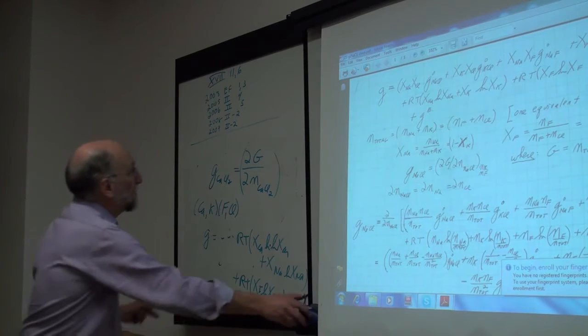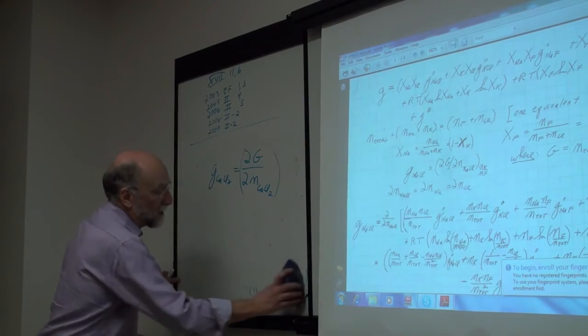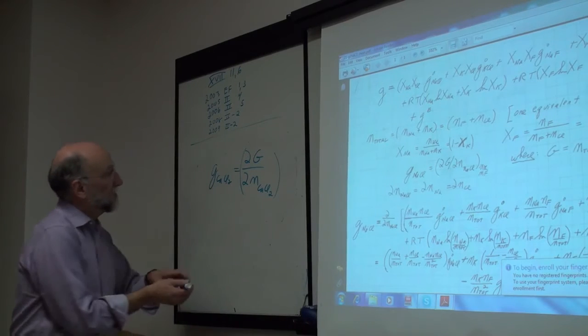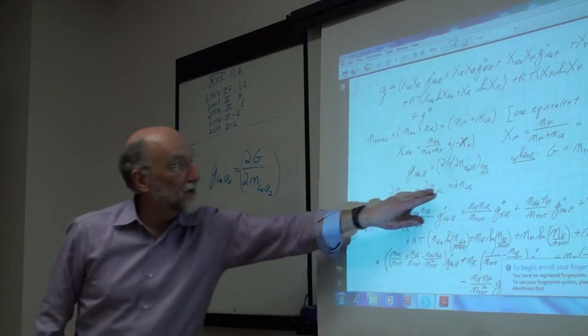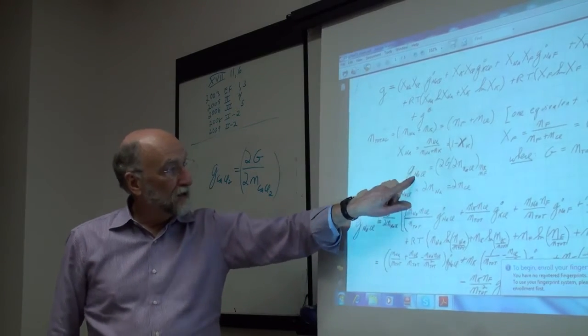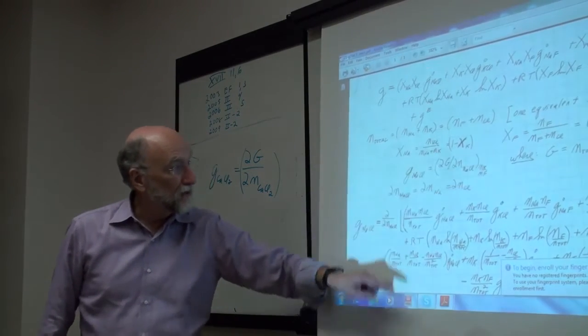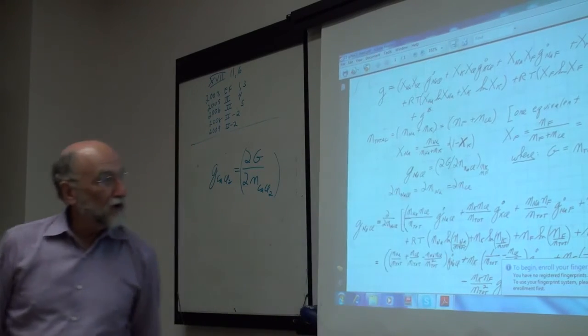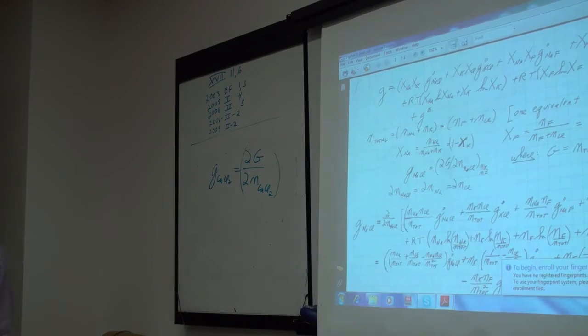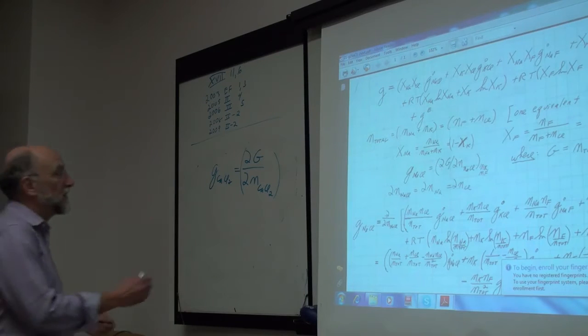So it's going to be the same entropy expression, but now the Gibbs energy chemical potential is dG dN sodium chloride. We're doing the same thing here. The G of sodium chloride was dG dN sodium chloride, and dN sodium chloride is equal to dN sodium plus dN chlorine, because you're adding the sodium and chlorine in equal amounts.